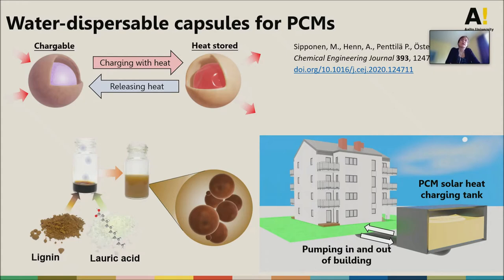And what was nice with this, so normally you need to have the phase changing material somewhere, otherwise it will of course leak out when it's melting. So we could show that this cycle could be done over 100 times without any change. And since these can be in aqueous dispersion, this could even be pumpable. So we could use this aqueous dispersion for this energy storage.